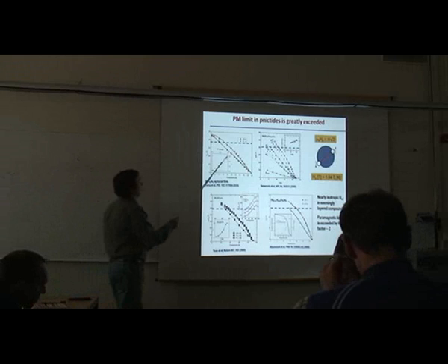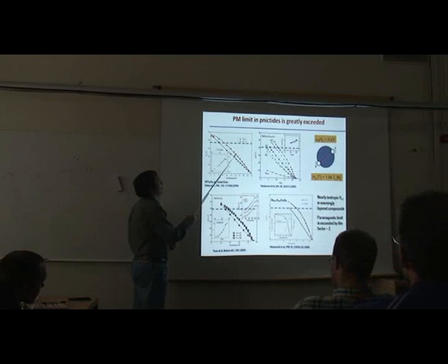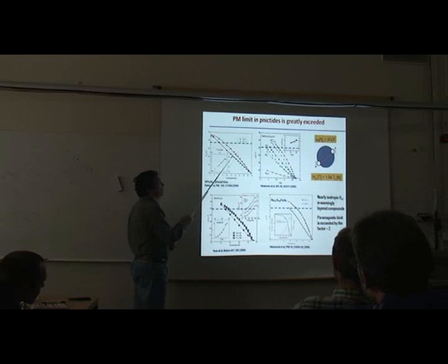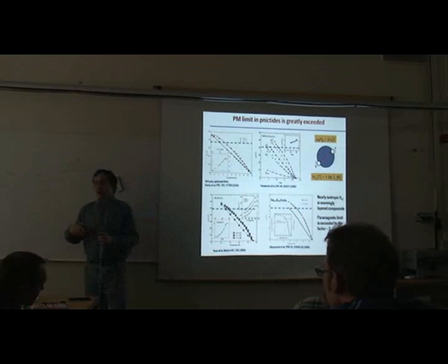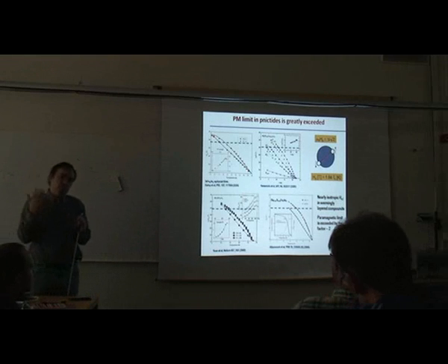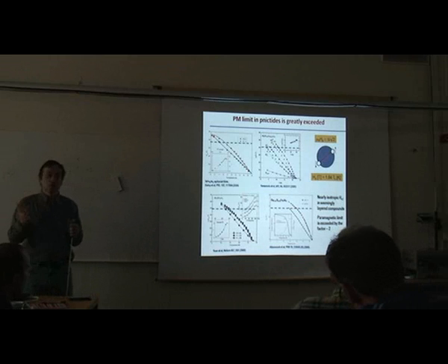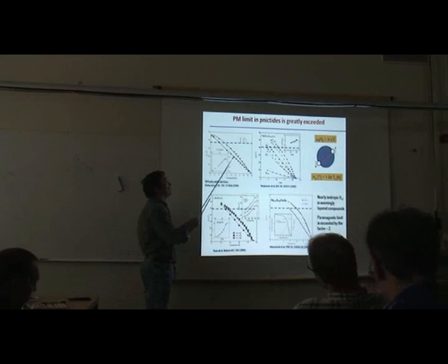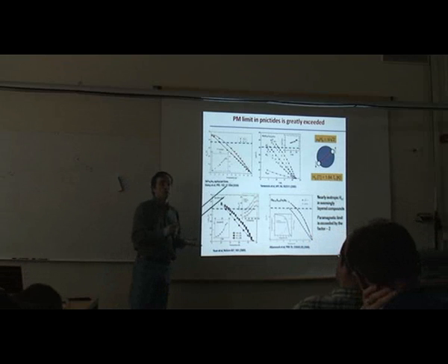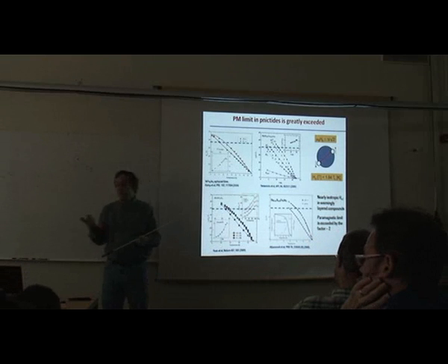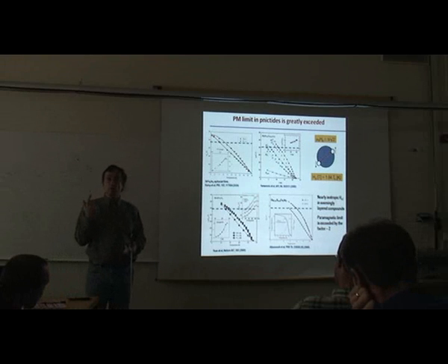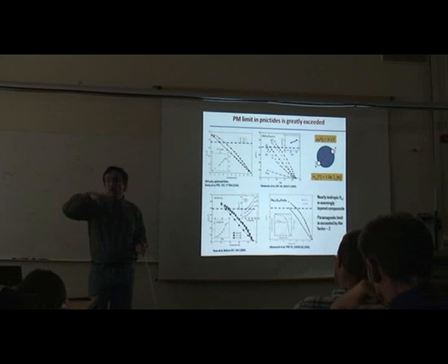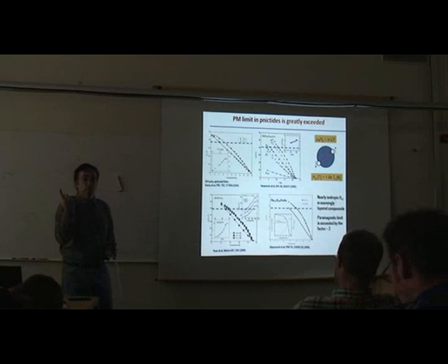But what's interesting is that this is Hc2 along the c-axis, this is Hc2 along the AB plane. There is very little difference between the two. Here too, and well, there's a difference, but not a huge difference. And Fermi surfaces suggest that we should have a two-dimensional highly anisotropic material. If we have a highly anisotropic material, then the difference between the field along the c-axis and along the AB plane should be large. Here it isn't. And that seems to suggest that maybe for these materials, the orbital pair breaking is not important, that maybe Zeeman pair breaking defines Hc2, and the Zeeman pair breaking is isotropic. Doesn't matter what direction the field is.